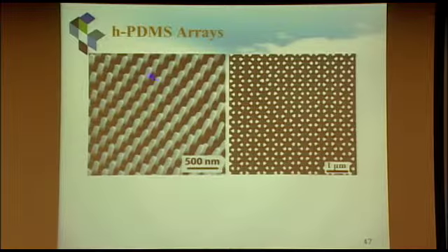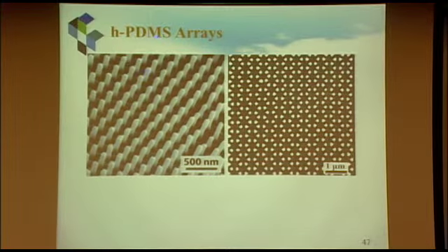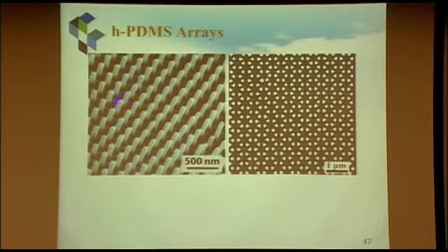So these are some of the PDMS things we put in, starting from the monomers, the polydimethyl siloxane. And then we use a hardened one. That's why I said H. The idea to use hardened is to increase the rigidity of these rods so that they don't collapse and then bundle together. And this is what we got. You see the very straight rods standing out.